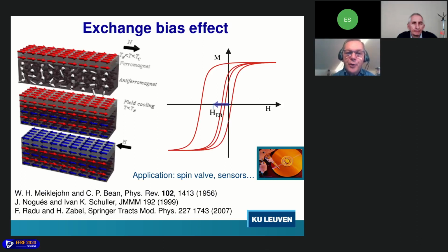Exchange bias then refers to the very strong magnetic coupling that is occurring at the interface between the ferromagnet and the antiferromagnet. And this is really an exceptionally strong coupling. The result of that is that when you apply a magnetic field to this system for trying to reverse the spin orientation of the ferromagnet, you have to apply a much larger field than for the ferromagnet alone before you are able to break this strong magnetic coupling at the interface.